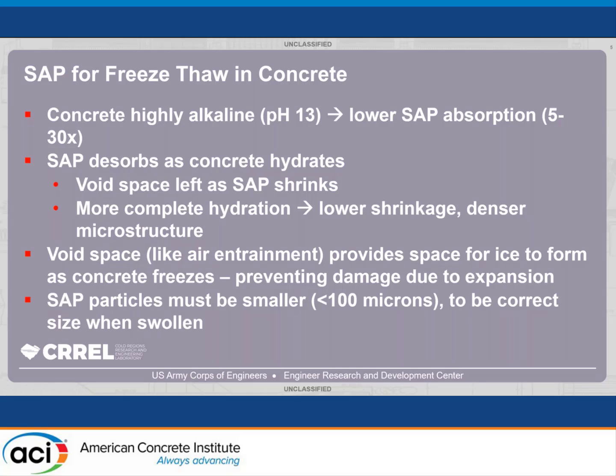The SAP particles do need to be a certain size. You can't just use any material, and we had to do some research and find one that was the size that fit for us. Because then when they swell and then desorb, they need to be the right size for concrete. So what we found in research is it needs to be under 100 microns.